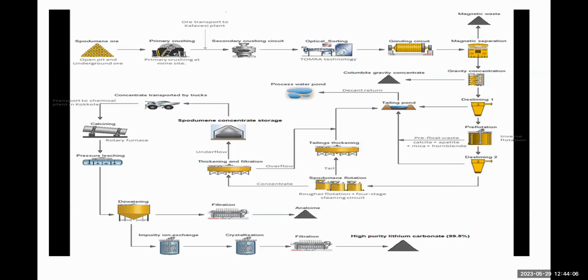We remove every organic matter that is present in the concentrate, so that at the end of the day, you can see the last drawing there that looks like sand, a heap of sand. You can see you're having 99.5% lithium carbonate or lithium hydroxide, depending on the kind of ion exchangers that were used in the process.